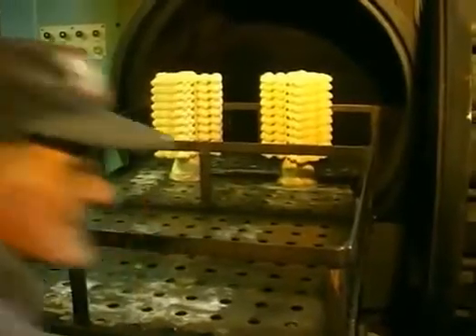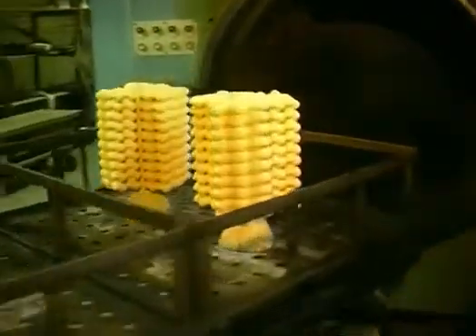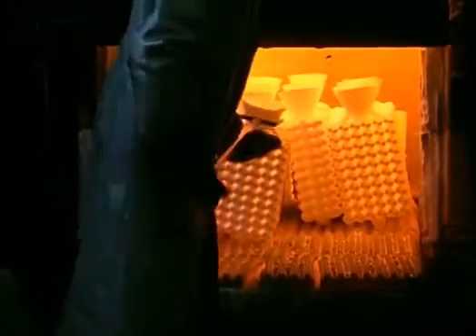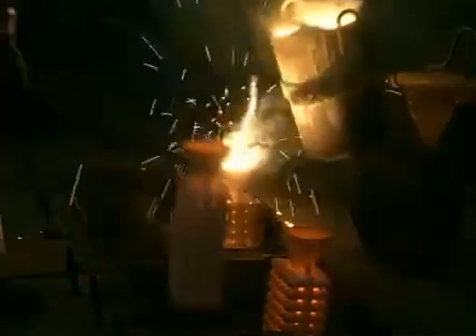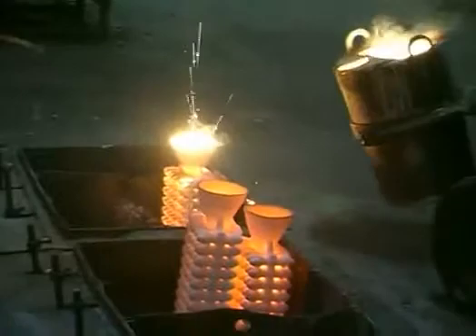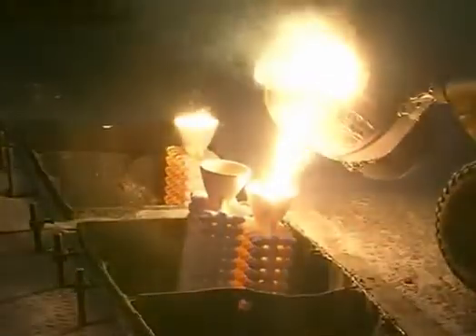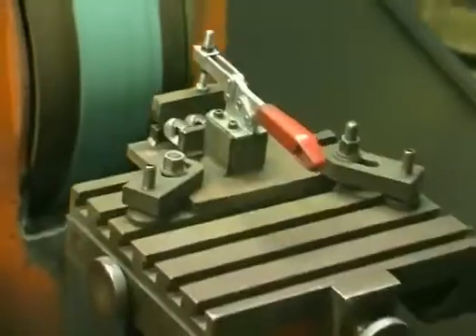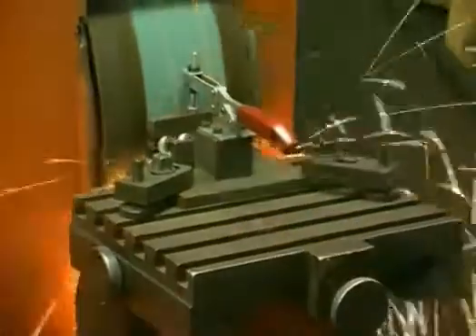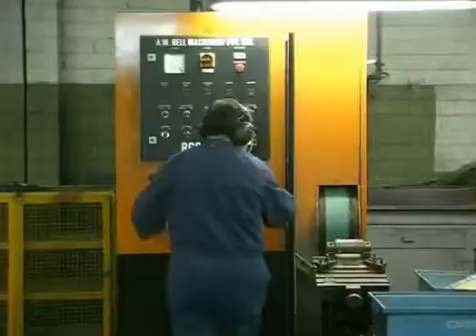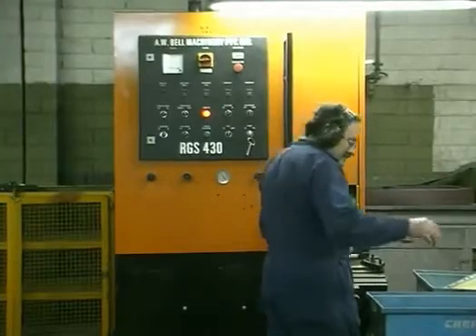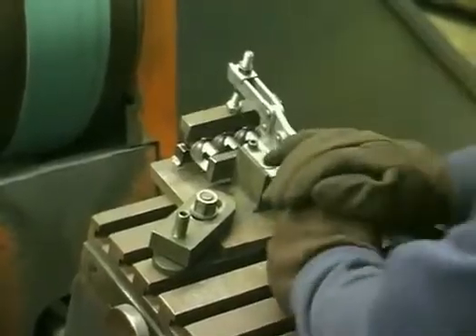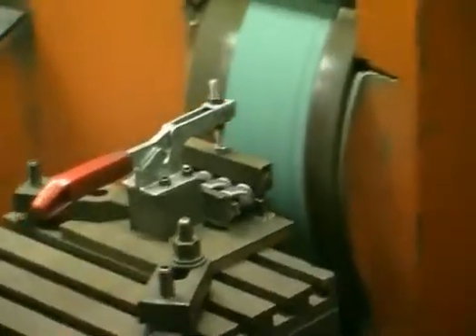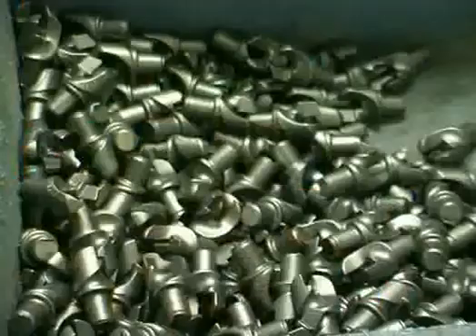Wax is melted out of the shell in an autoclave at 150 degrees Celsius. Any remaining wax is burnt out in a furnace at 750 degrees. The temperature is then raised to 1000 degrees just prior to pouring. The components are broken out of the shell and ground to size. This partially automated linisher has improved productivity by 700% and has eliminated rejects due to over-grinding.